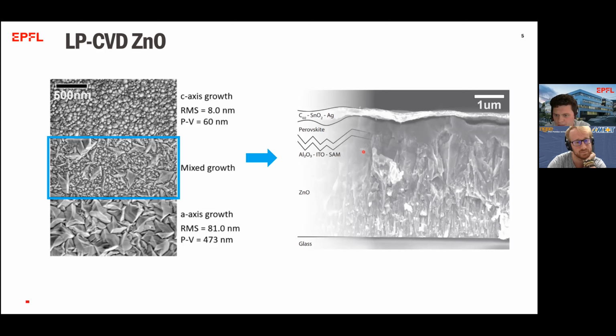So it's very reactive, so we had to interject that. On top of that, we then spin coat a perovskite layer. It's a triple cation, the one that is very heavily used and got famous by the initial paper by Michael Saliba. And you can nicely see how it covers these textures. We finished the device by thermally evaporating C60, depositing tin oxide from ALD, and finally the top electrode, silver.